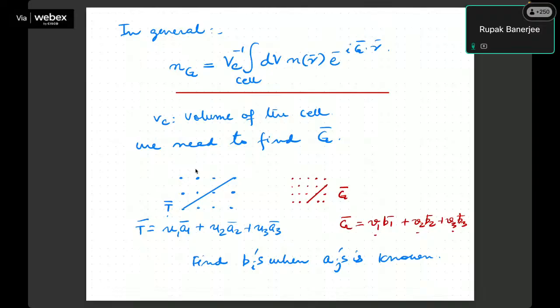So just see what I do. Just like in real space, I have T, which is u1a1, u2a2, and u3a3. And in G also, similarly, because obviously the length scales will be different and it is actually an inverse length scale because it is 2π by a. You will see going in real space from one point to another, you can go using T. Similarly, going from one point in reciprocal space to another, you can do anything using G. However, if you try to go somewhere in between where G is not defined, that is not part of the reciprocal space. That is the important thing. Okay, there cannot be any point in between where your lattice translation vector can't take you. That is not an acceptable translation vector in either real or reciprocal space.